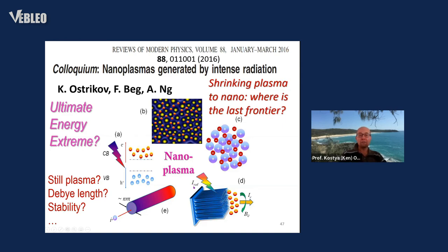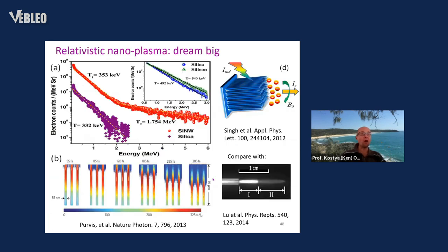When, for example, very high intensity and ultra-short laser pulses, typically in the femtosecond range, are irradiated on an array of nanowires or some nanoparticles, those nanoscale objects literally explode. And while they explode, the electrons are injected and the ions follow, and oscillating electron-ion clouds are formed. That creates those unique, localized, very high density nanoplasmas, which can also have energies generated even in the relativistic domain. And they also develop and evolve with time.